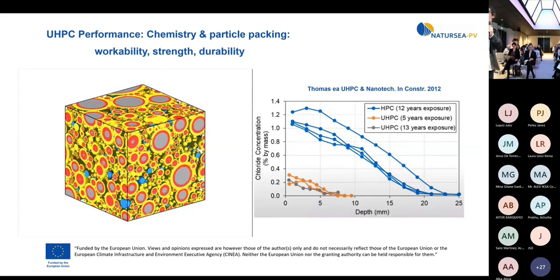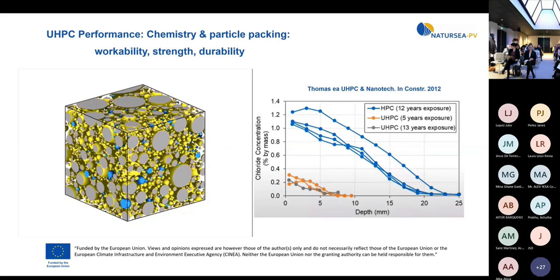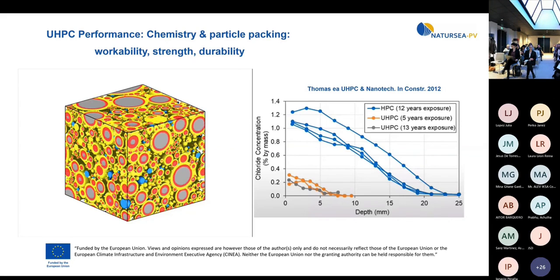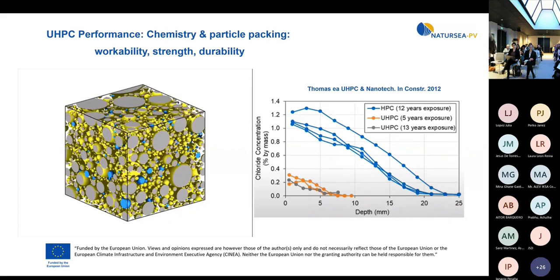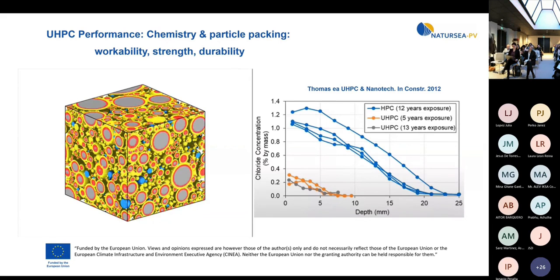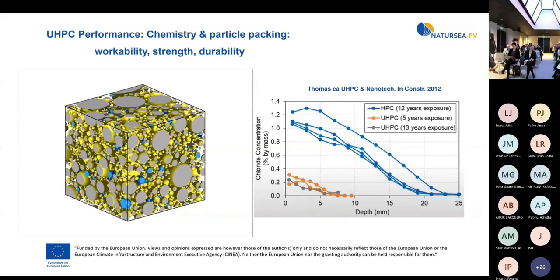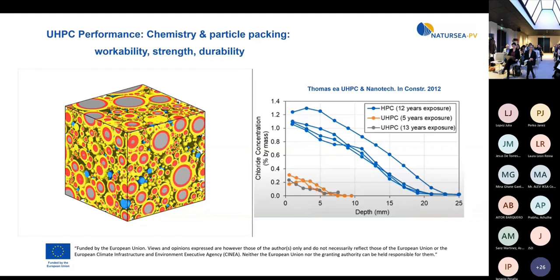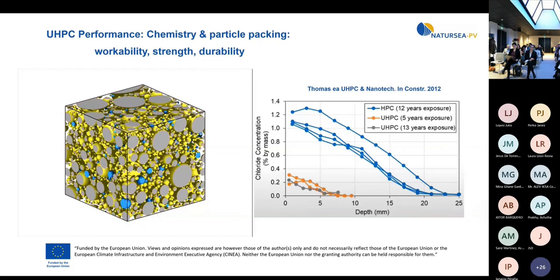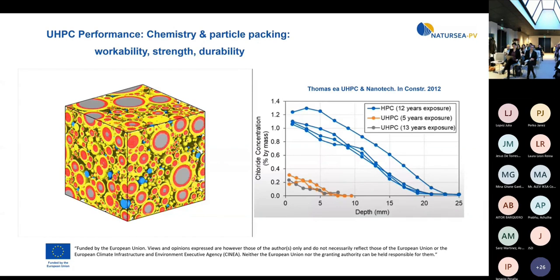Here I found one from the literature, Thomas. This is a high performance concrete, and here we see the chloride ingress for the ultra high performance concrete, and you can see really how much less chlorides are ingressing in ultra high performance concrete.